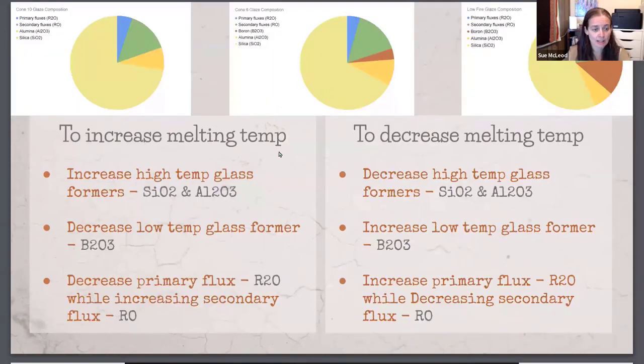So just to recap, strategies: if we want to increase melting temperature, we can increase our high melting temperature glass formers, silica and alumina. We can decrease the boron, because the boron is helping the glaze to melt at a lower temperature. So we lower the boron, which raises the melting temperature. Or we can decrease the primary flux, which raises the secondary flux, and that's also a way to increase melting temperature. If we want to lower the melting temperature, we just do the opposite.